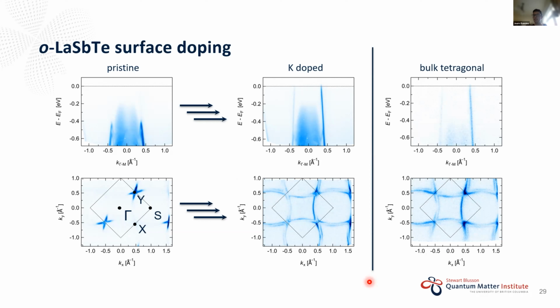So with this, it really seems that the energy scales here are small enough in terms of the relative balance between the lattice distortion and the gain in electronic energy through the distortion. These energy scales are very similar, and even small changes, for instance, in bulk doping just by roughly 10%, or by doing pure electron doping, if you wish, through potassium deposition, we can tweak the balance between these energy scales.